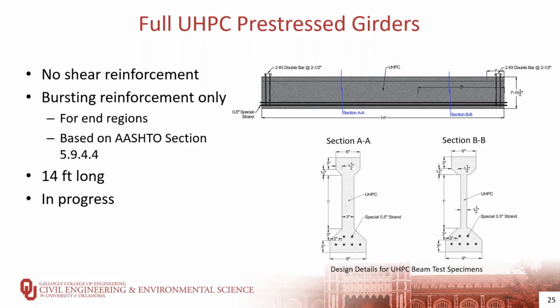For the full UHPC pre-stressed girder design, no shear reinforcement was added, nor top steel to offset the high tension stresses, and only bursting reinforcement was added at both ends based on AASHTO section 5.9.4.4. The web was also reduced in these girders similar to the hybrid beams, and that can be seen here from section BB in the bottom right figure as well.